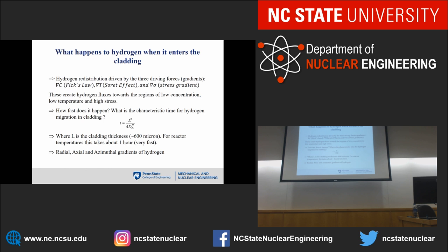So how does it happen? What is the characteristic time? You can consider it like this: t equals L squared over 4D, where D is the diffusion coefficient and L is the length that you have to travel. And that's about an hour at the reactor temperature. So it's very fast. So it gets in, I have a temperature gradient, I can respond to that very fast.